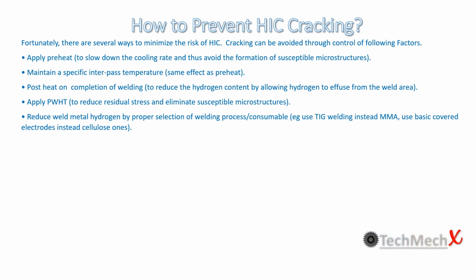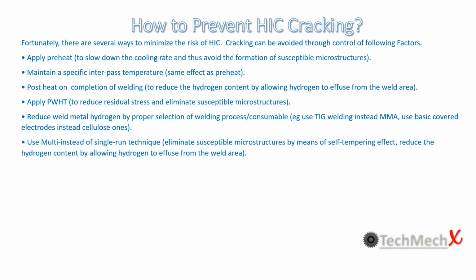Use TIG welding instead of SMAW welding. Use basic covered electrodes instead of cellulose electrodes. Use a multi-run instead of single-run technique. Eliminate susceptible microstructure by means of the self-tempering effect, and reduce the hydrogen content by allowing the hydrogen to diffuse from the weld area. Use a temper bead or hot pass technique, with the same effects as above.